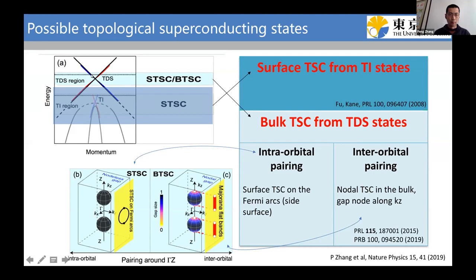Also, if we dope the material to put the Fermi level near the bulk Dirac cone, since this bulk band structure may affect pairing, we need to discuss different pairings. If the intra-orbital pairing dominates, then the gap will be S-wave, similar to normal iron-based superconductors. Then on the side surface, we know there will be a Fermi arc for the Dirac metal. This side surface will be topologically superconducting, same as the Fu-Kane model.